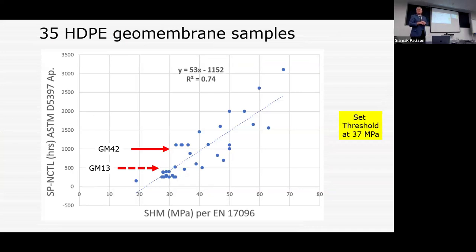35 samples. Okay. It's not nearly as good as the stress crack data that I saw. R squared is 0.74, but it's the best we have. You'll see the intersection here for the GRI 500 hours, be around a strain hardening modulus of 30. 42 is up around 1,000, and that number would be close to 40. So keep that in the back of your mind when you see the rest of the specification.